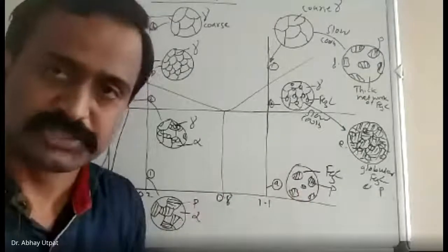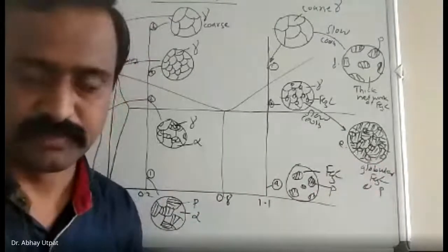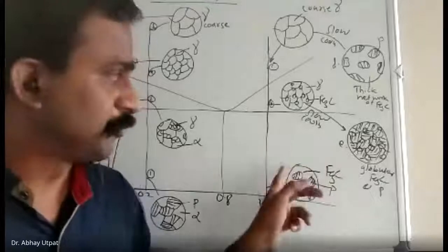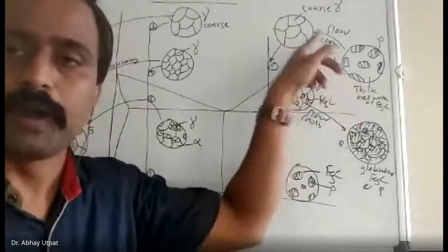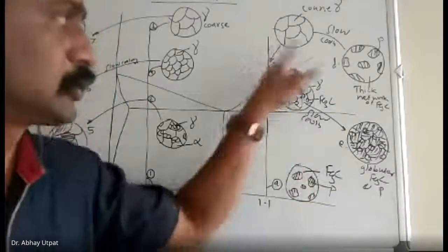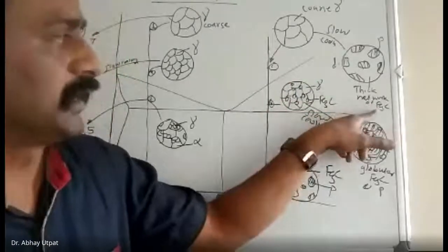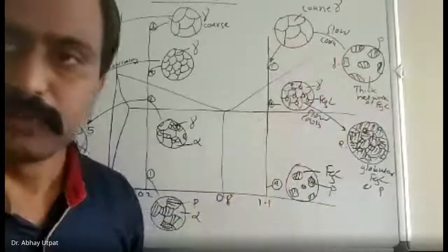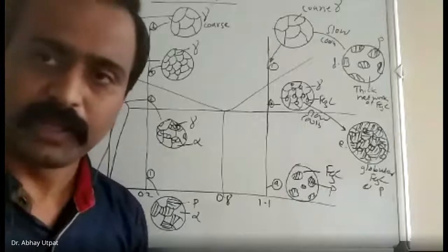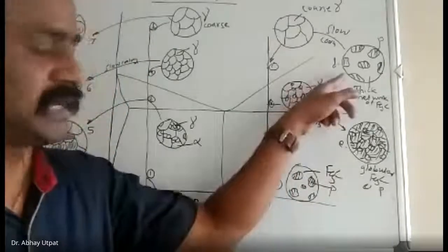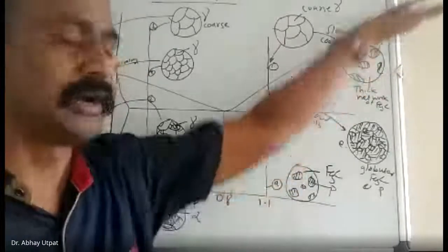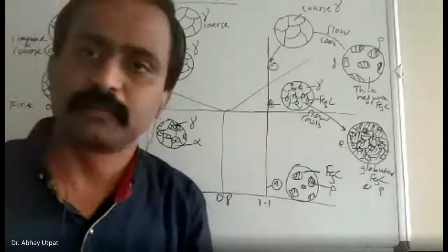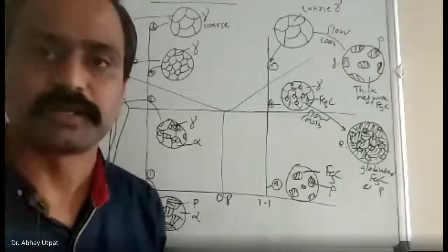This is a question. How to write the answer? Answer will be, if we carry out full annealing of hypereutectoid steel, the slow cooling will give thick network of cementite. Thick network of cementite has poor mechanical properties because once a crack is propagated, it will continue throughout the object and there may be chances of breaking of the complete object.